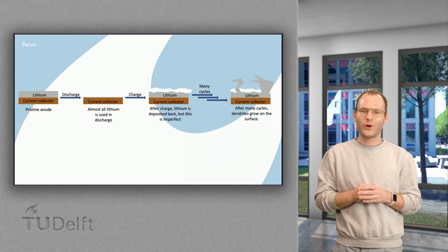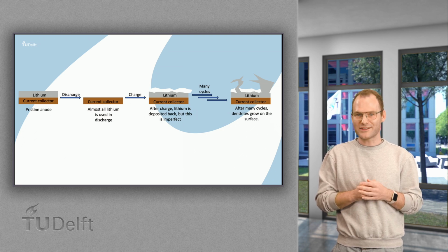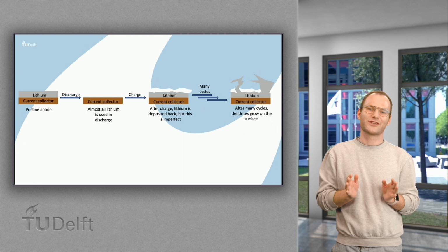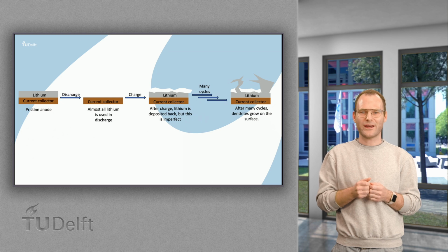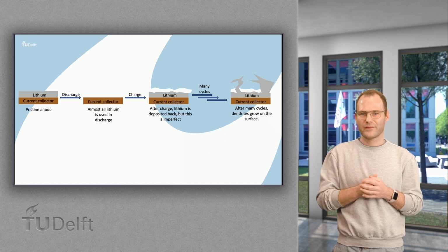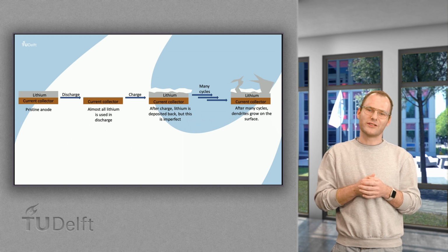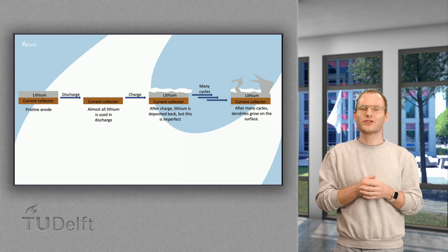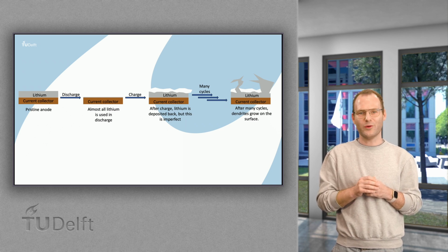When we look at the anode, one could argue that we just have to use metallic lithium. This is very true and is heavily investigated by researchers. However, until now, metallic lithium tends to give dangerous batteries because of lithium dendrite formation. Over many cycles, lithium is not uniformly packed back in the anode. It will make many different tree-like structures. When these grow, at some point they will touch the cathode, which will cause the battery to shortcut, which can result in fires. Therefore, lithium is dispersed between graphite. This will lower the energy density, but will give much safer and more stable batteries.